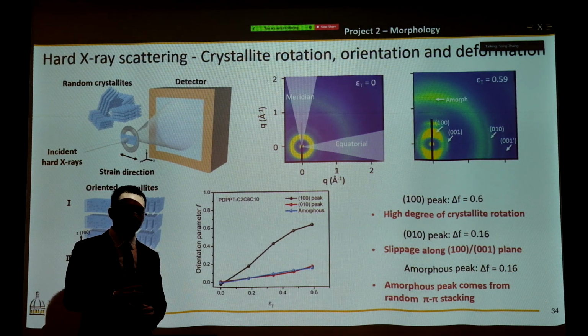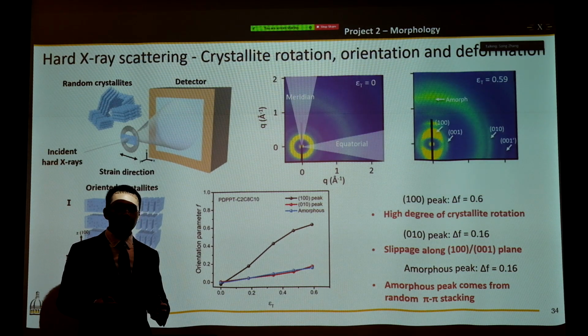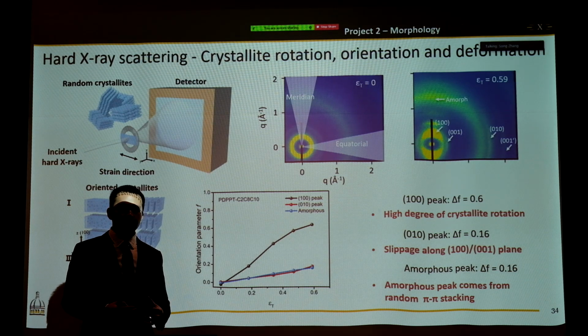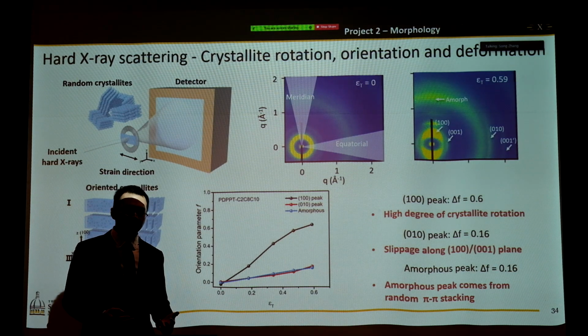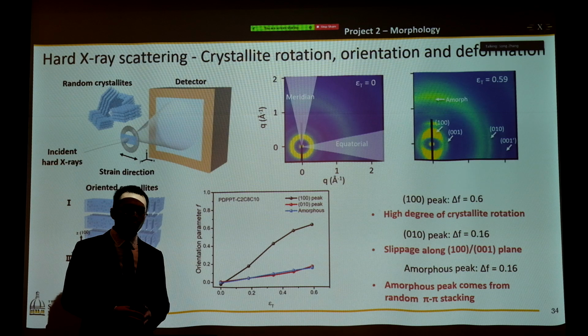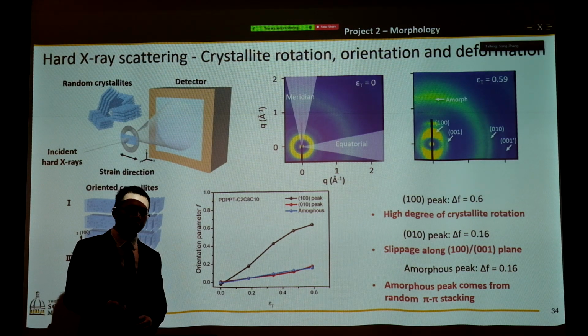Okay, another contribution we think we make to the field is the determination of the amorphous peak. Previously in the literature, people have had different opinions on the origin of the amorphous peak. Some people said it's coming from randomly oriented side chains. Some people said it's coming from randomly oriented polymer pi-pi interaction. And our observation seems to favor the second explanation, because we saw a delta F value exactly the same as that of the 010 peak.